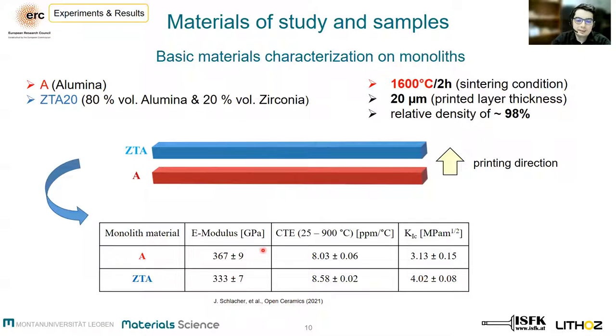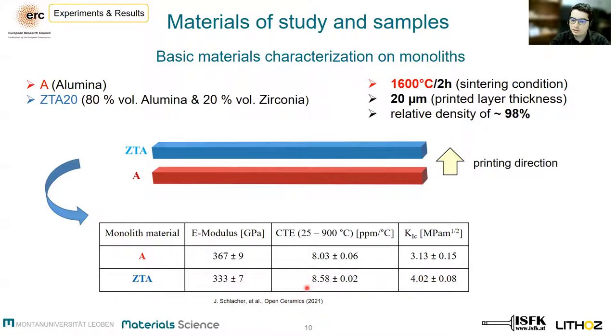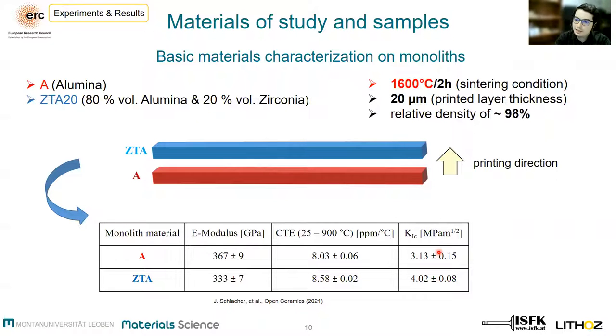Furthermore, we can see that the CTE of zirconia-toughened alumina is higher than that of alumina. So in a laminate architecture, we would expect compressive residual stresses in the alumina region and tensile residual stresses in the zirconia-toughened alumina. Finally, if we take a look at the fracture toughness, the one of zirconia-toughened alumina is significantly higher than that of alumina. This is well known from conventionally manufactured ceramics as the toughening effect of transformation-toughened zirconia ceramics.